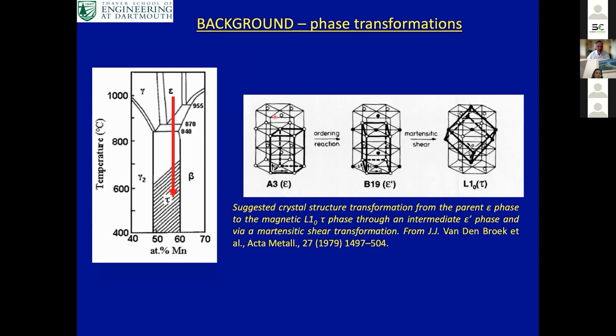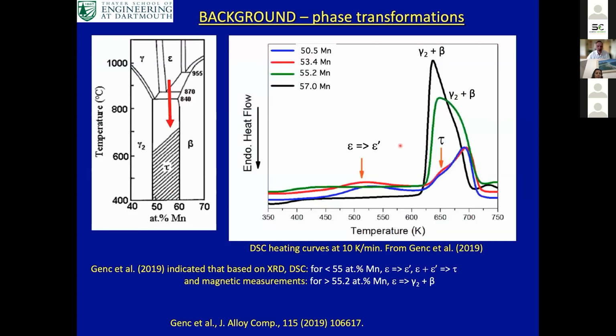It's a little bit more complicated than that, possibly. Some people have suggested that the epsilon doesn't simply transform to tau, but there's actually an ordering reaction from the hexagonal phase that transforms into this ordered phase, which is now orthorhombic, and that the ordered phase then undergoes a martensitic shear into the tau phase. This is still a little bit contentious. There's a little bit of evidence for that, though.